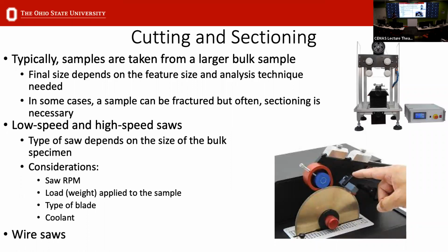But there are actually a lot of considerations when using these, even when just sectioning your sample. As you can see here, there are various fixtures for the saws that you can put odd-shaped samples in and get ready to cut. So when cutting a particular sample, you want to keep in mind the saw revolutions per minute, how much load you're applying to your sample, and the type of blade you use.